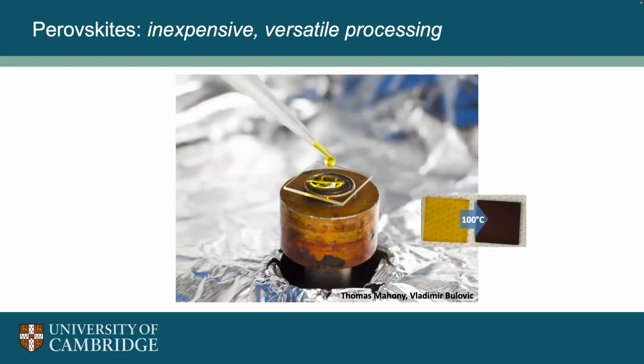So how we process them, this is what we do in the lab. Typically we dissolve the ionic precursors in solvents and essentially make inks, and we cast them down onto these substrates and spin coat them in the lab at a few thousand RPM. So it spins and forms these very uniform crystalline films, which are yellow here, and then we heat them at 100 degrees Celsius, which is quite a low temperature for semiconductor processing, at least. Remember the 1,000 degrees that silicon would need. But by doing that, we form these very nice crystalline films, and this is the PV absorber that we use in our solar cells.